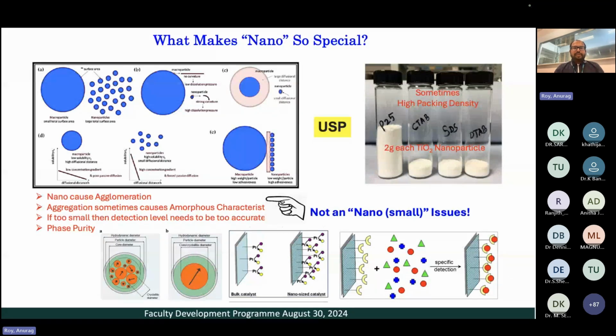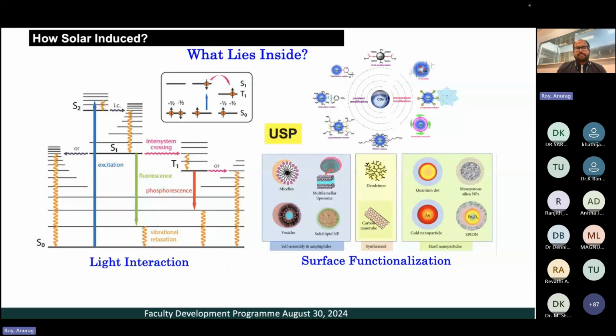Okay, so if there are pros, there are some cons. What is the problem with nanomaterial? Nanomaterials cause a high degree of agglomeration. If you produce some nanomaterial, there is a high chance of agglomeration because of their small size. And aggregation sometimes causes amorphous characteristics. That's what you can see when you go for X-ray analysis of your nanomaterial: a higher noise-to-signal ratio compared to a bulk material. And if it is too small for the detection level, the measurement may never be accurate. And last but not the least, the phase purity. If you want to develop some complex material in its nanoform, phase purity or phase development is a very crucial factor. I will show you in a couple of seconds in some other example.